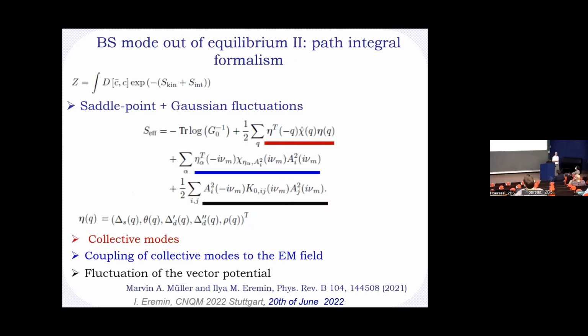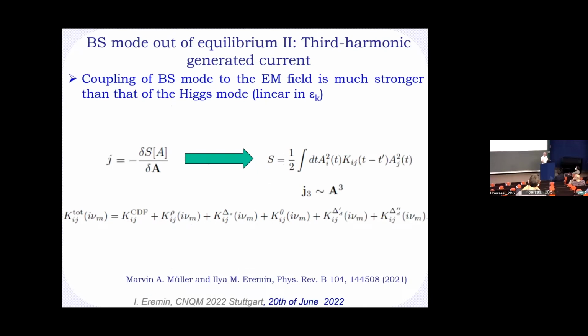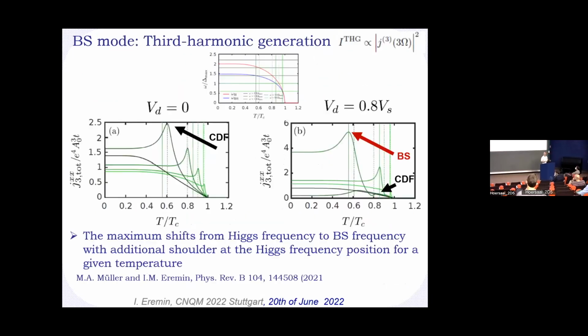So you have to move to the path integral formulation, where you also take into account your long-range Coulomb interaction and basically do all the machinery by introducing all the collective modes in the dominant and subdominant channel and coupling effective modes to the electromagnetic field. And now, if you do that, you can also compute the current and the third harmonic generation, which will be proportional to the third order of the vector potential and contains all the contributions coming from the collective fields.